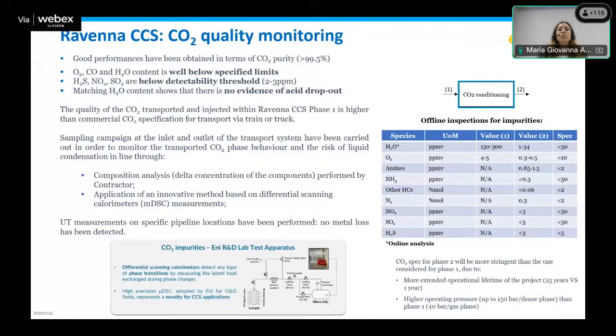This is also confirmed by other UT measurements that have been done on pipelines and that confirm that there were no metal losses. Last thing to be mentioned: this phase was in gas phase, while the second phase will be at higher pressure and in dense phase. So this is why we expect a more stringent CO2 specification for the next industrial phase of Ravenna CCS. This was all about the Ravenna CCS phase 1.